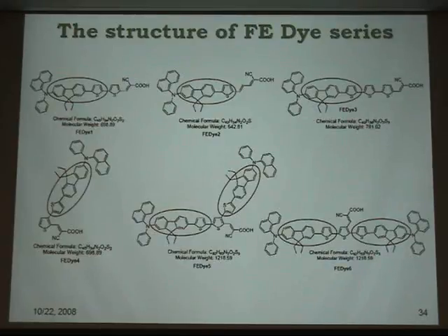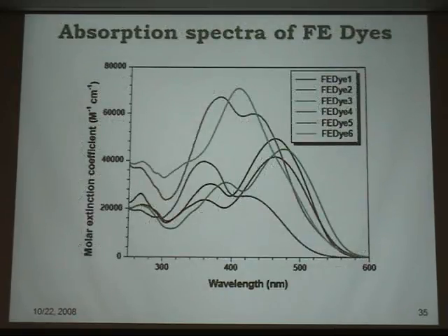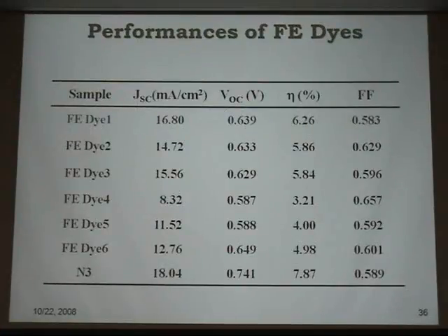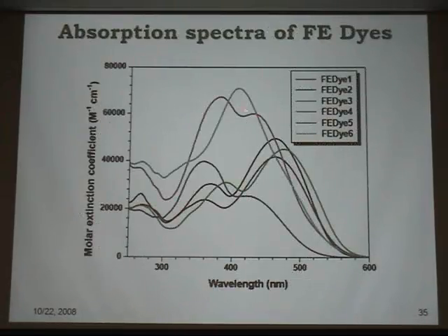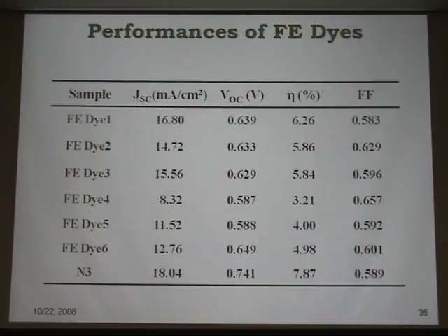Now, later on, we made different dyes, and we used a similar approach. Measure the absorption coefficient and try to correlate this with performance. Now, if you think dyes 5 and 6 will perform best, it can be very wrong. Actually, FE dye 1 performed the best, not 5 and 6. So the molar absorption coefficient does not tell you the whole story.